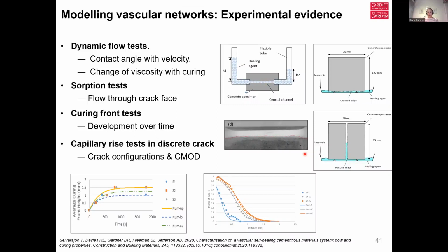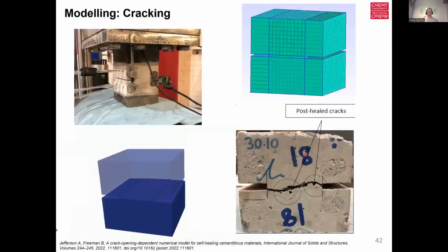We then looked at sorption, so how it would flow through a crack face. We looked at the curing front of these, so at a distance away from a concrete surface, how does that curing front develop over time to be able to give that solid material in the crack. And then we looked at capillary rise tests in discrete cracks using different crack configurations and crack mouth opening displacements to look at the kinetics of that capillary rise. And then our colleagues were able to use all of this information together with their special finite elements and cohesive zone models that I've been working on, to look at modeling the cracking. So here we have a cube which is just being pulled apart under tension. We're supplying healing agent to the crack zone, and we're able to model that cracking stage and the flow of healing agent into that crack.